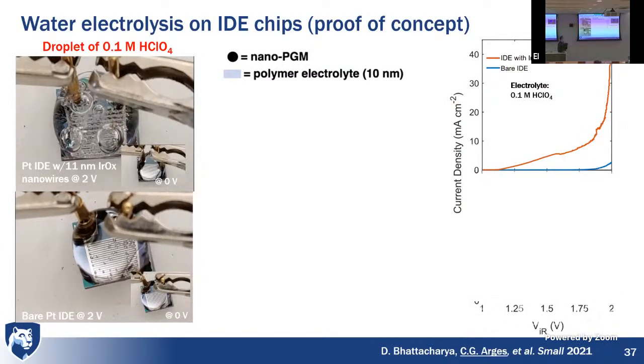So here's our platinum interdigitated electrode, and we put 2 volts on it, and we get some water electrolysis, as indicated by this hydrogen and oxygen gas. But if we put iridium oxide nanowires on this platinum current collector, which is a good water oxidation catalyst, with no volts applied to these little circuits with this perchloric acid droplet on it, they look identical, right?